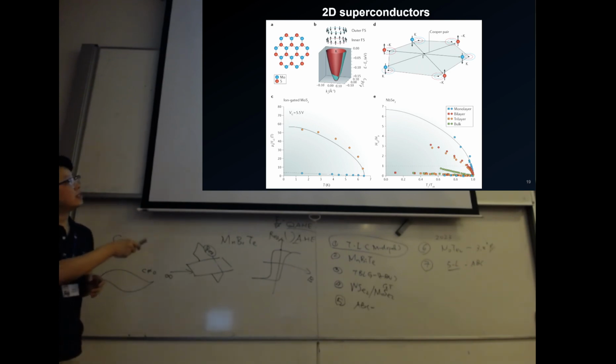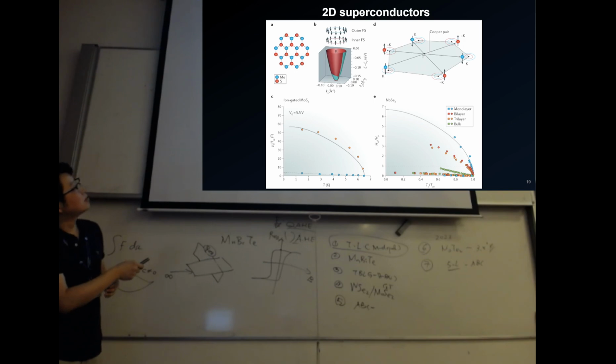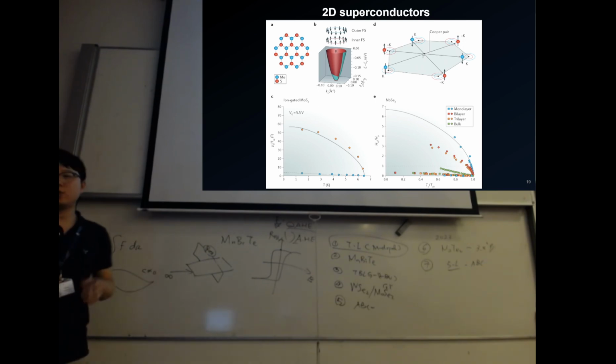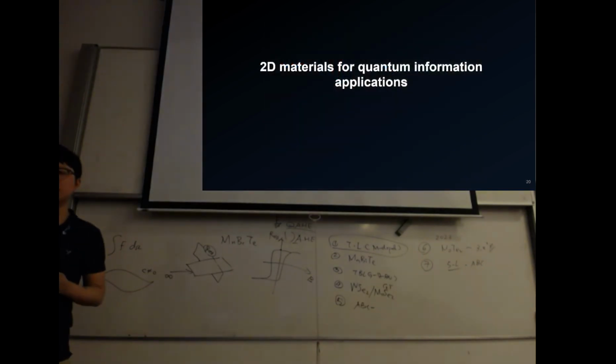So it's pretty low, for example, for niobium diselenide. It should supposedly be 1 to a few Tesla, and actually the superconductivity persists up to 6 or 7 times higher than the Pauli limit, which means more than 10 Tesla in this case. This is in units of Tesla. We can see people went up to 50 Tesla, and the superconductivity is still there. The in-plane application of an external magnetic field doesn't kill the superconductivity. So this is one of the very specific properties of 2D Ising superconductors, specifically for TMD materials, for example. So this we have to also mention once.